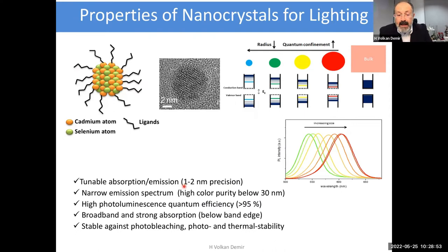And with certain chemical routes, we can make them quite narrow. It turns out that given our calculations, if you have a spectral window within a full width at half maximum of less than 30 nanometers, actually for human eye, it is spectrally pure. So this high color purity is another benefit. For certain routes, including those especially cadmium containing, we can make quite high efficiency, over 95% in solution, reaching near unity. And in certain cases, cadmium-free options can also match this high level of performance.